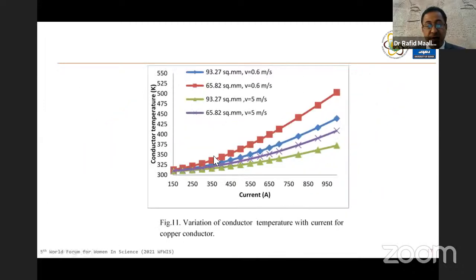Also, this is for current and conductor temperature for 3 conductors with different speeds of air. This is for copper conductor when the velocity is 0.6 meter per second, and this is for velocity 5 meter per second. We see that the higher curve is for low cross section because the dissipation is very low.